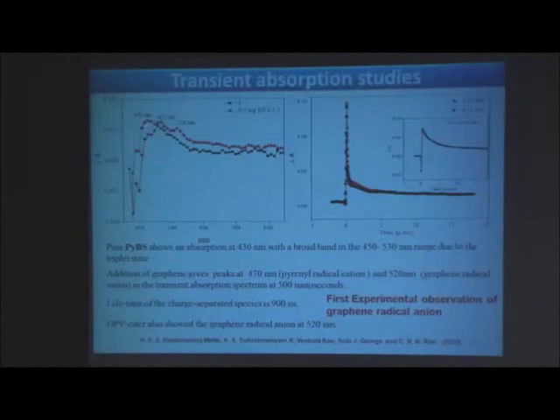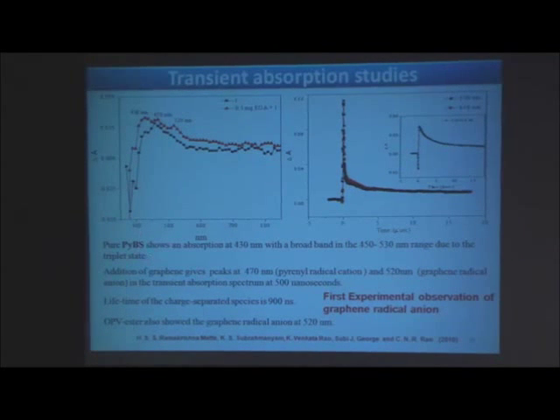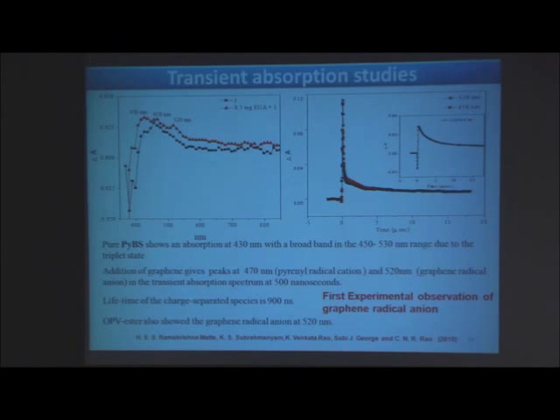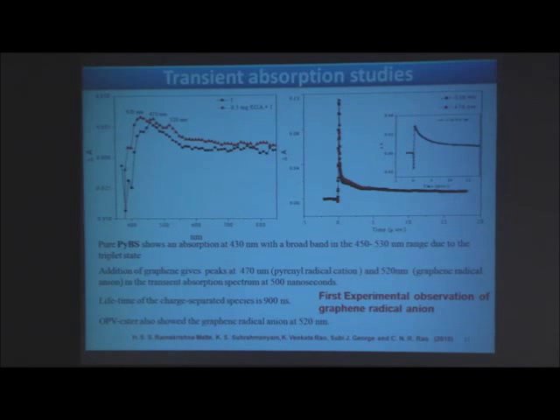Another property of graphene is that given any pi system, any aromatic which gives you fluorescence, when you put graphene, the fluorescence is quenched. It immediately quenches the fluorescence. Why does it do that? It is because of electron or energy transfer. And we have shown in the case of pyrene and these molecules, it is actually electron transfer. We have done transient spectroscopy, and here is the transient spectra to identify graphene radical anion formation because of electron transfer from the aromatic to the graphene. I will not bother you with this, I shouldn't have put this. It will take too long to talk about it.